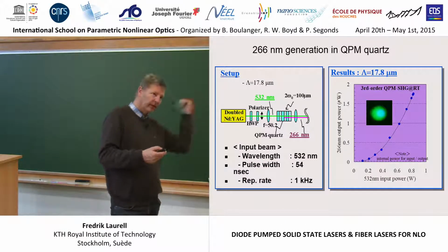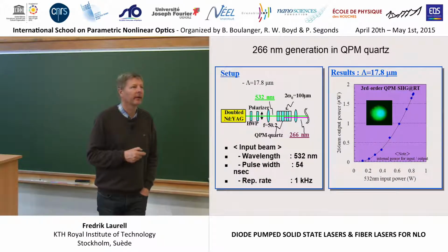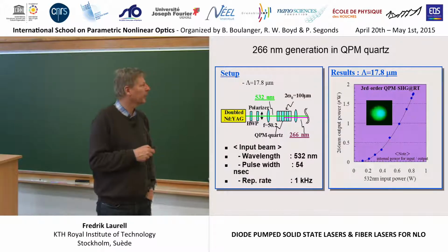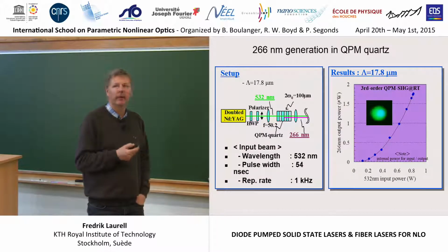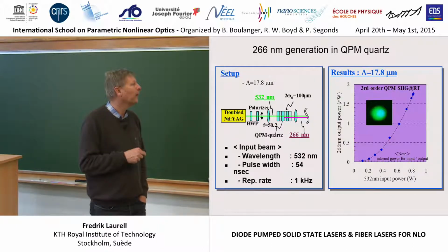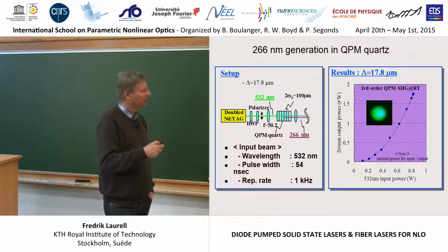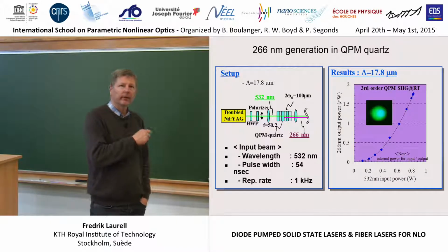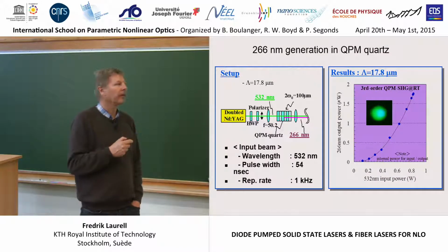If you want to go in the opposite direction, we don't have any good material that we have been able to grow the same way, and no ferroelectrics that we can pull, at least to very short wavelengths. There is now some material coming out from one of our previous PhD students, Junji Hirohashi. But a general feature for these UV materials is that they have very low nonlinearity.